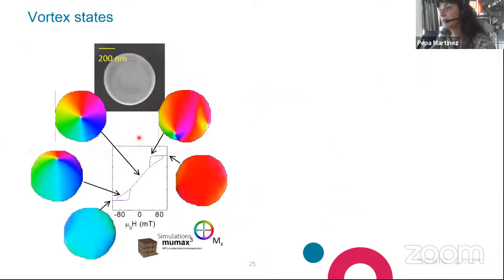Well, these nice structures are very nice for applications because they constitute 4-state logic units, and they are also nice because they exhibit a number of interesting excitations at high frequencies that can be used, for instance, for creating spin waves or fabricating spin torque oscillators, etc. So we wanted to see whether we are able of studying these objects using our nanosquids. This that you see here is a particle fabricated in our clean room, consisting of permalloy with dimensions, as you see, of almost 600 nanometers in diameter, okay?